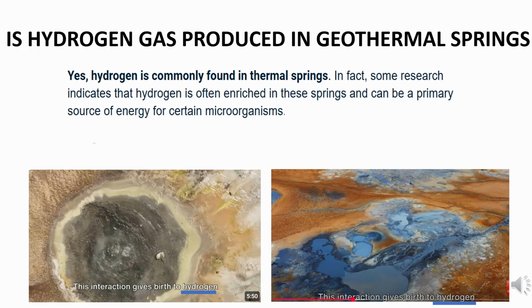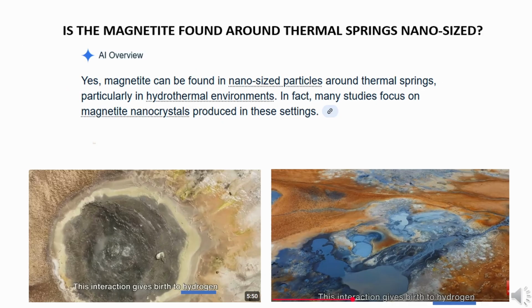In fact, some research indicates that hydrogen is often enriched in these springs and can be a primary source of energy for certain microorganisms. Is the magnetite found around thermal springs nano-sized, less than 100 nanometers? Yes, magnetite can be found in nano-sized particles around thermal springs, particularly in hydrothermal environments. In fact, many studies focus on magnetite nanocrystals produced in these settings.